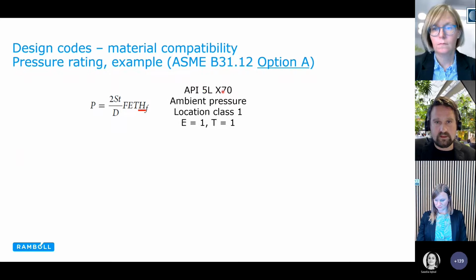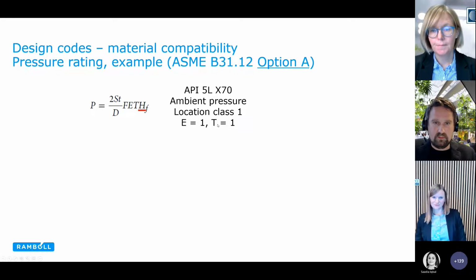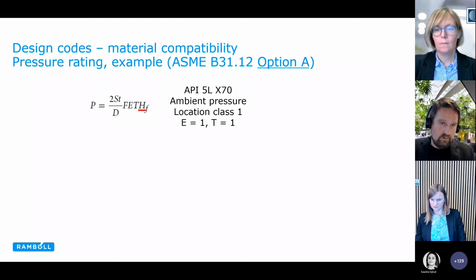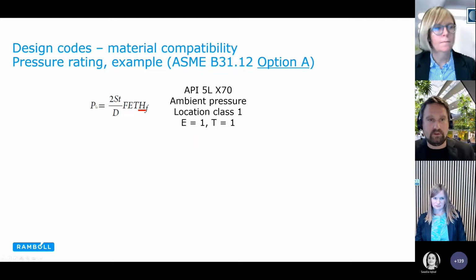I'm just going to take an example here where I have API 5L X70 steel, so a yield strength of 485 megapascal, and we put it at ambient temperature. We put it in location class 1, which basically means it's out there in the field, far away from humans, and we set the temperature derating and the longitudinal joint factors to 1, just to consider normal conditions there. And then we go into our table, and so S would be the yield strength, T is the wall thickness, D is the outer diameter, and P would be the resulting allowable pressure.